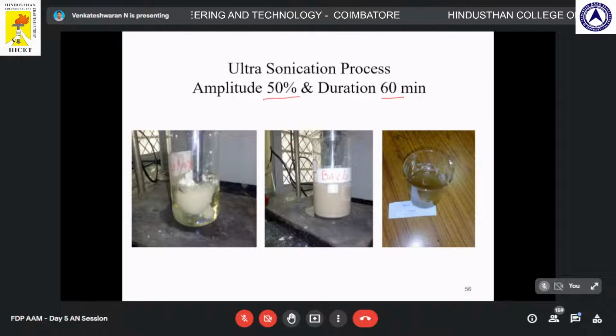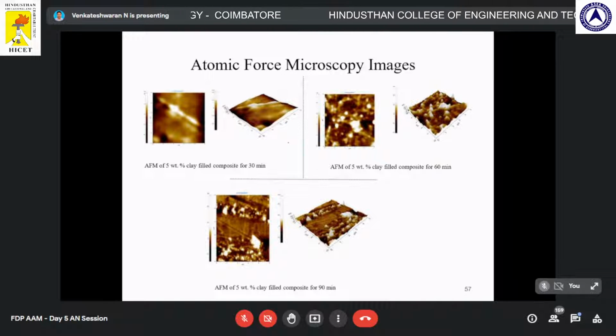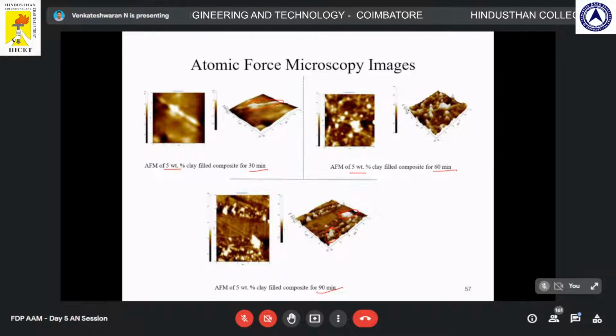So next we have to analyze these materials, right? To the naked eye we are telling that it is okay, but that is not enough. So we went into AFM microscopy to show the AFM of 5 wt.% nanoclay for 30 minutes, 60 minutes, and 90 minutes duration. Okay, so 5 wt.% for 60 minutes, we can see a large number of nanoclays. These white dots are nothing but the nanoclay, which are somewhat distributed. Whereas for 30 minutes, we are seeing only a small amount of nanoclay, and nanoclays are mostly accumulated here. Similarly, when it goes to 90 minutes, some accumulations are occurring here, right?